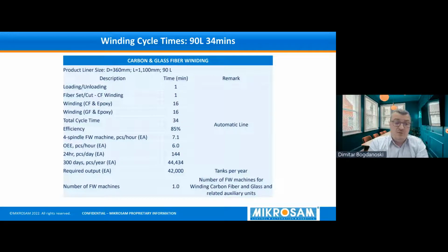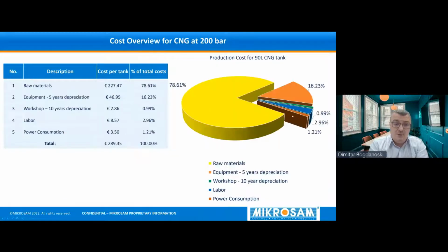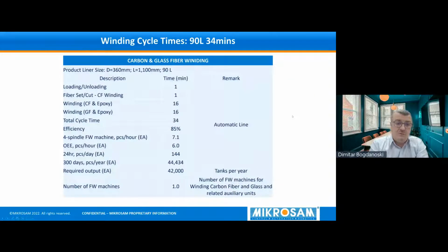We took an overall equipment efficiency of 85%, and with four spindle operation, we come to 6 cylinders per hour. In total, in 300 days, we can reach around 44,000 pieces per year, which meets the required output of 42,000 cylinders per year. In order to realize all of this, we need only one filament winding machine.